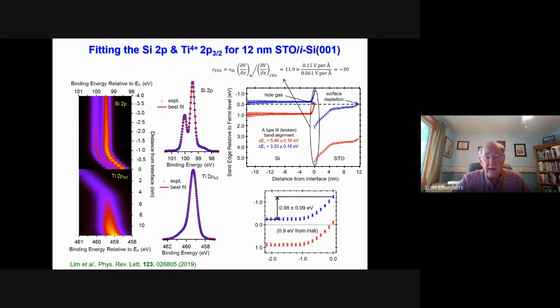And the last thing I want to point out is that you notice that in the STO, there's this strong downward band bending, which means that all of the free carriers in the STO are going to accumulate at the bottom of the film, and there are going to be enough of them that they're going to screen the titaniums and the niobiums down there and make them look like they have a lower valence than what you'd expect based on their nominal valence on the lattice. And so that explains the weird looking spectra for the titanium and niobium.